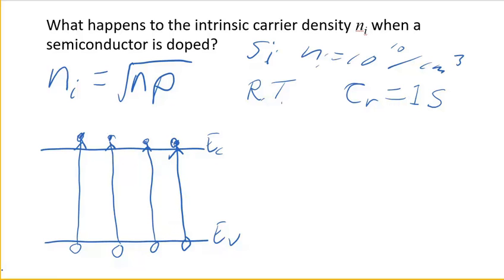Let's think about what happens when the very first electron is promoted to the conduction band. How does it get there? So you have an electron in the valence band and it has to go up to the conduction band. It gets there by having thermal energy given to it. Where does it get it? It borrows it from the solid in the form of a lattice vibration bumping into it, a phonon. So the electron borrows some thermal energy from the solid to get up to the conduction band. Now there's an electron in the conduction band. The solid has a little bit less thermal energy to it. The solid has gotten colder.